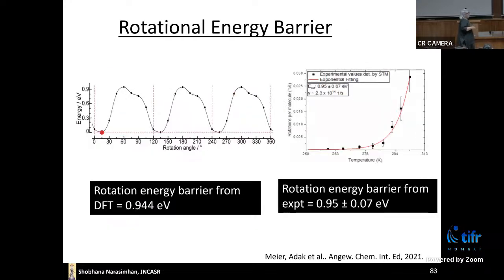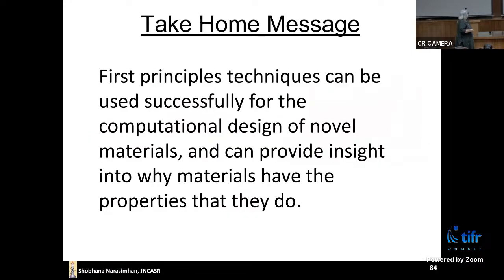And we can also calculate the barrier for this rotation. And that's also something they can measure experimentally by doing experiments where they change the temperature. And the agreement was sort of embarrassingly good, because you don't normally expect such good agreement between calculation and experiment. So we got 0.944 eV and the experiment said 0.95 plus or minus 0.07. Okay, so let's see. Okay, I think I'm done.